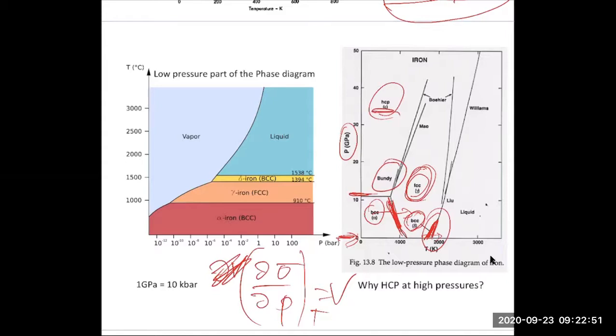Because if you precipitate in a matrix, you are under enormous coherency stress, right? Because this matrix is enormous and is essentially imposing its volume on you. And that's the same as a very effective large pressure. And so you can see HCP. This phase diagram is sort of consistent with the fact that you can observe HCP iron under highly constrained volume or lattice parameter conditions. Okay, let me show you a few more fun phase diagrams before we end.